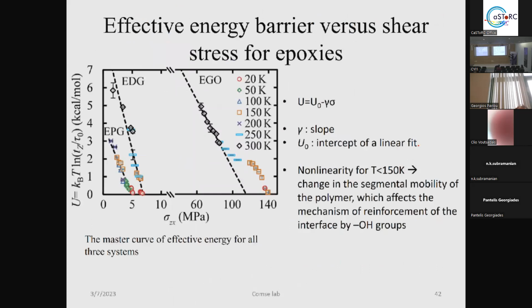And of course, we were able to calculate the effective energy barrier versus the shear stress for epoxies for the three different systems. And you can see also here the different adhesiveness that depicts on this plot. In the epoxy pristine graphene you have a very small energy barrier in terms of energy landscape, and then bigger energy barriers, and of course, even bigger in the EGO. Here we see a nonlinearity, which is due to the different segmental mobility of the polymer that affects the mechanism of the reinforcement because of the OH groups. They are working as brushes, let's say.